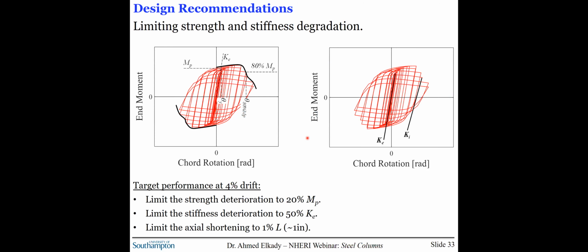Now, using the data from these simulations, we were able to develop seismic design recommendations. Essentially, we used the simulated responses to extract many response data related to the rotational ductility, the strength, and the stiffness deterioration. For instance, we evaluated the rotation at which you lose 20% of your plastic moment capacity. And based on all these parameters, we were able to propose improved design recommendations for better ductility and stability in steel columns.